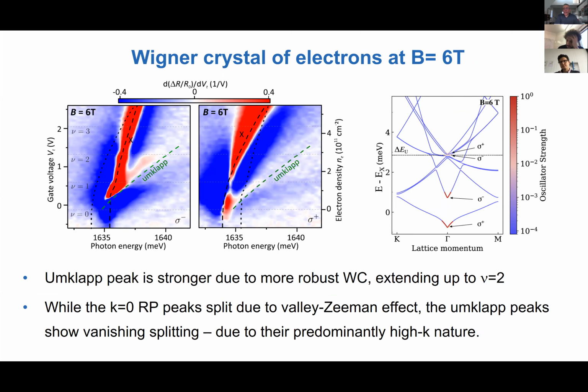Now, because of the at least partial quenching of kinetic energy, the signatures become more robust at finite magnetic fields. So this is at 6 Tesla for 2 different polarizations. And you can see that particularly for sigma minus polarization, now the umklapp peak is quite strong. Part of this is not that this polarization is expected to be stronger, but basically the energy detuning between the sigma minus umklapp peak and the sigma minus K equals 0 peak is smaller than that of sigma plus. And this is precisely, again, due to the electron-hole exchange interaction, which basically makes sure that the excitons at large momenta do not see the magnetic field to first order. They are linearly polarized, they mix the two valleys, and therefore upon umklapp scattering, the splitting between the two is going to be very small.